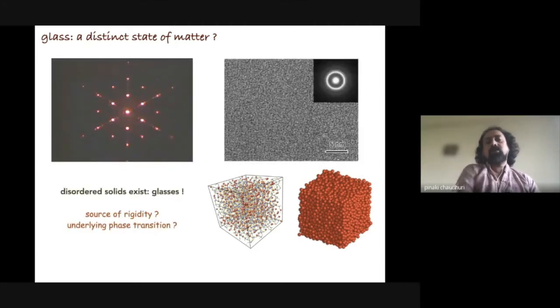If you look very closely at the structures, for example, if you do some scattering experiment where you throw X-rays or laser into the structure and look at the reflection or the diffraction of it, then you can see that for the crystal you get very nice periodic patterns, which give you some information about the order that exists within the crystal. This is on the left hand side of this panel.